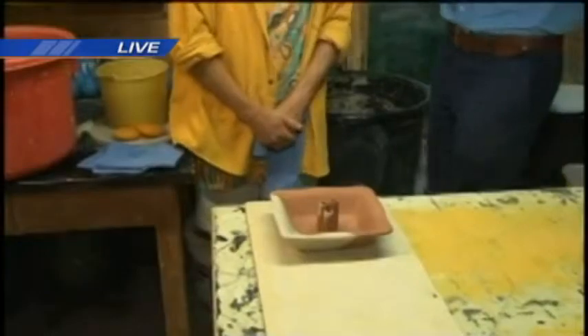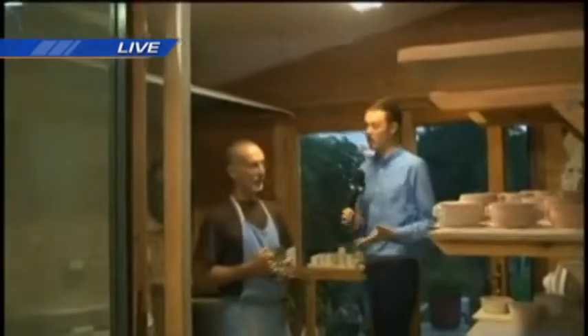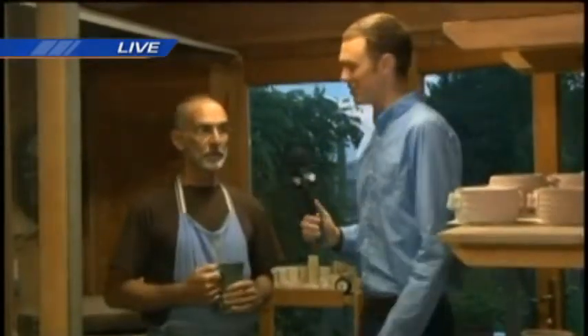In just a little while it'll be ready to go into the glaze firing, into the kiln. Thomas has been working with pottery since 1989. These kilns are on — I can smell them and feel the heat. Usually we don't turn them on this early, but you guys show up pretty early in the morning, so we start them at about 5 o'clock. The firing process takes about nine hours in the glaze firing. Every hour we set them up another increment from 1 to 7 on the dials, and it goes from ambient temperature to about 2,300 degrees for a final firing. What's the total time from throwing to the shelves? Start to finish, depending on how dry the air is, about five days to a week.